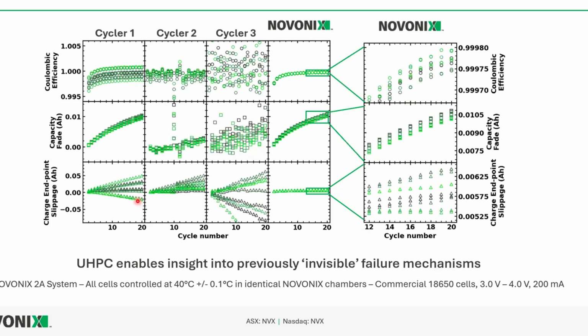And this really comes down to the accuracy and also the bias between charge and discharge within these channels. If you're charging a cell and you're always slightly overcounting compared to discharge, you're always going to have basically fake slippage. And the more biased towards overcounting on charge you are, the higher your slippage is going to be. And if you're biased towards overcounting on discharge, based on the accuracy spec of your equipment, then your charge endpoint is going to slip backwards because you're always going to have a larger discharge capacity than is real. So this is why slippage isn't necessarily a very used metric, because it just isn't possible in almost any other type of cycling equipment.